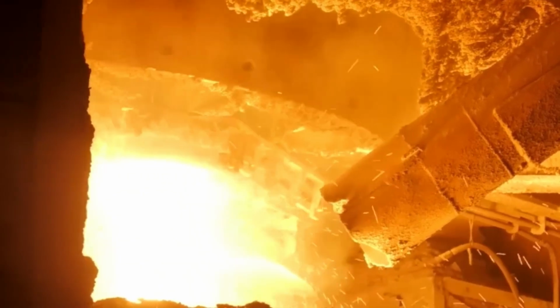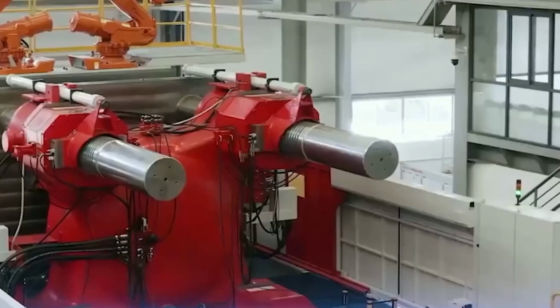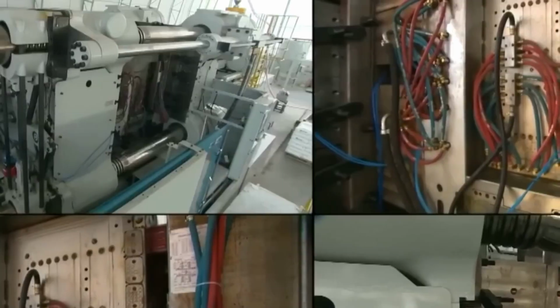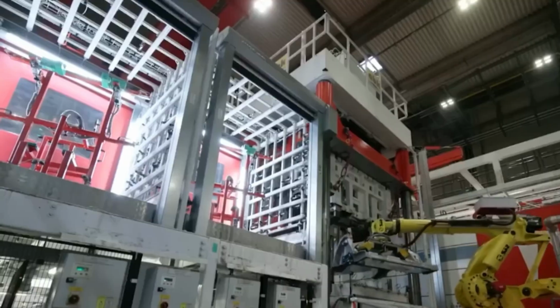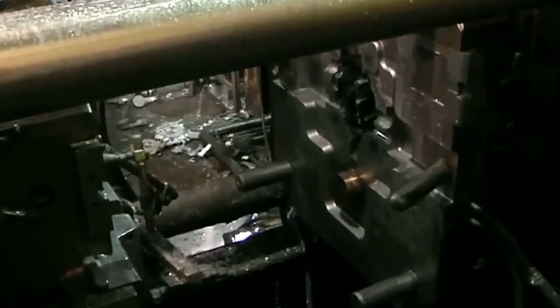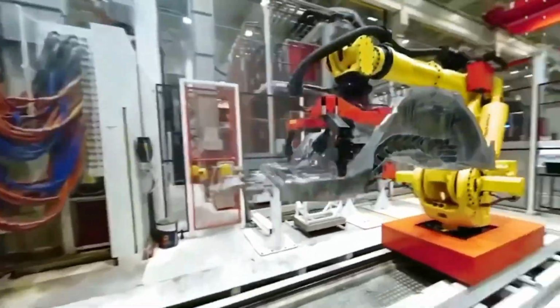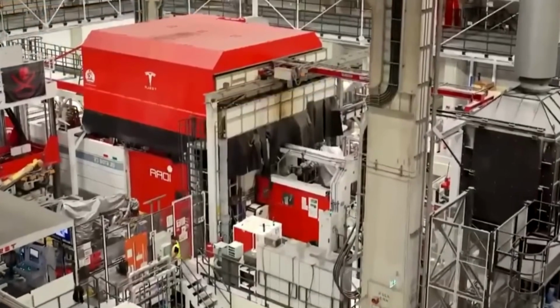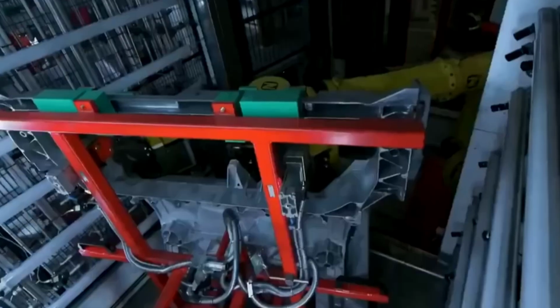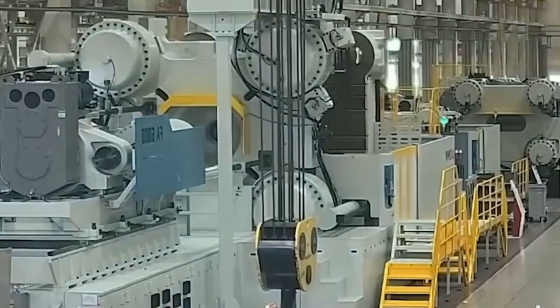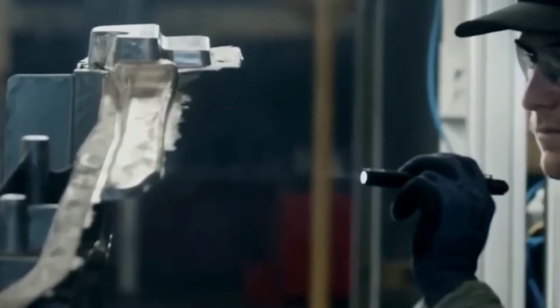tremendous force. After injection, the metal solidifies inside the mold, and the red-hot casting is extracted at a temperature of around 400 degrees Celsius. It's immediately submerged in a cooling bath, where the temperature drops to about 50 degrees. This isn't just about speeding up the process. Rapid cooling eliminates a number of casting defects and improves the mechanical properties of the material.